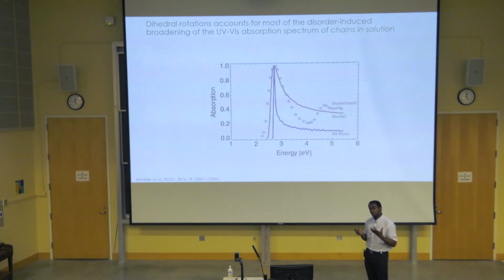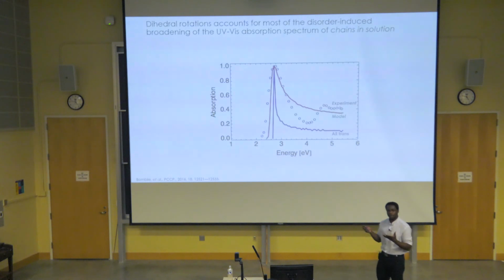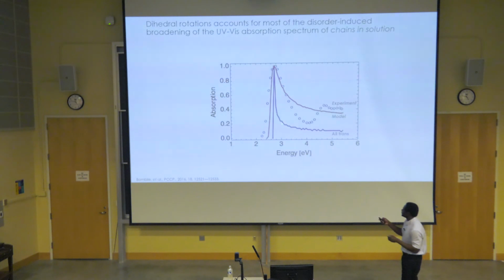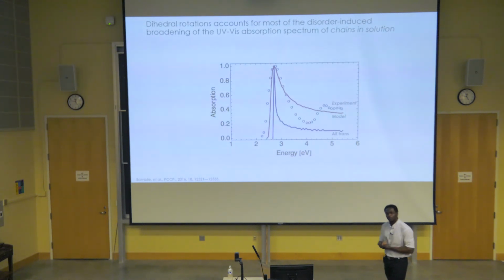We wanted to understand how much of the broadening of the absorption spectrum comes from dihedral disorder alone, to understand how important dihedral disorder is in affecting the electronic properties of the chain. So this is what we've shown here. We don't capture the whole broadening, simply because obviously dihedral disorder alone does not represent all the disorder, but it represents a significant part of it.